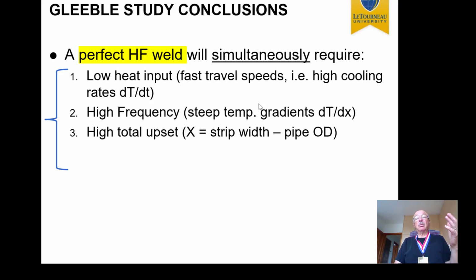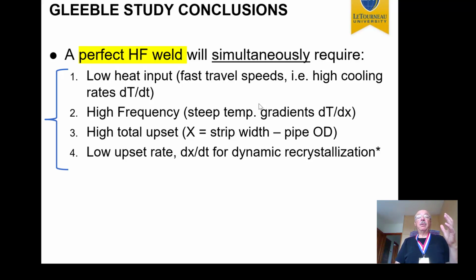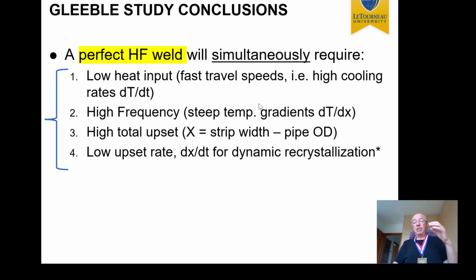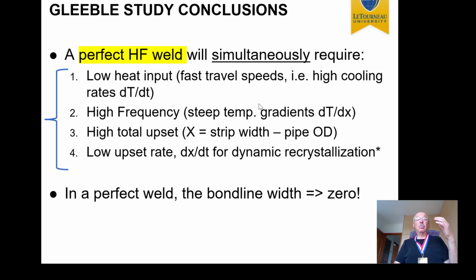But at the same time, the total upset had to be high to squeeze out a lot, and very surprisingly, the rate at which this provided the best grain size and push out was a low upset rate. And here's a little bit of a contradiction. So if you travel really fast, your upset rates will be high, yet you really need low upset rates not to work harden the material. So finding the balance between those makes a perfect weld accomplishable with low probability.